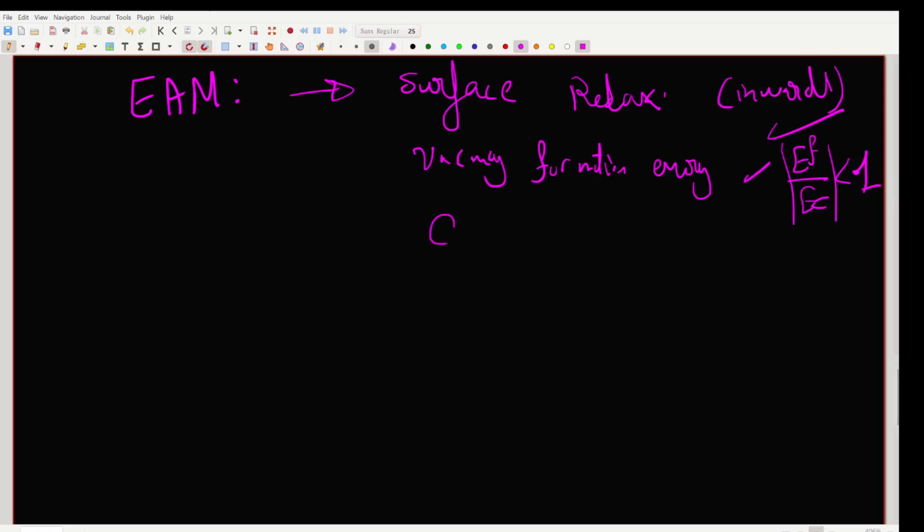You actually violate the Cauchy relation, right? You don't get C12 equal to C44. That's the correct behavior, right? And depending, of course, on the quality of the embedded atom method potential, you can actually study phase transitions, something which you couldn't do with pair potentials. But you really need a high quality embedded atom method.